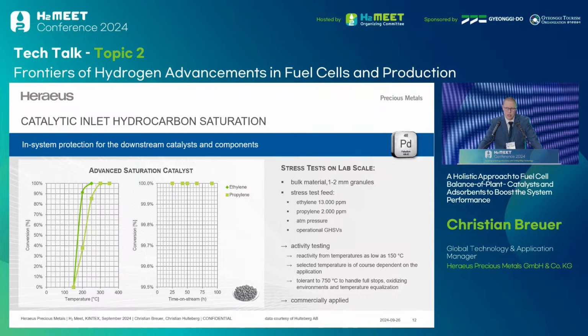Why use a saturation catalyst? The saturation catalyst, operating nicely in a temperature window around 200 to 300 degrees C, is there to specifically saturate ethylene and propylene. Because if those stay in the gas and go into the pre-reformer, it will coke and lose its activity, and then in the end the main reformer will lose its activity, and then the stack might undergo troubles with coking prematurely.